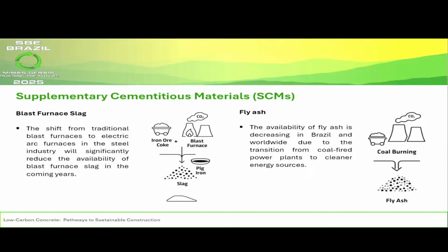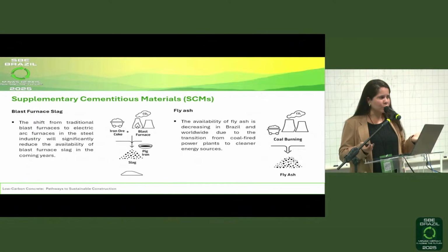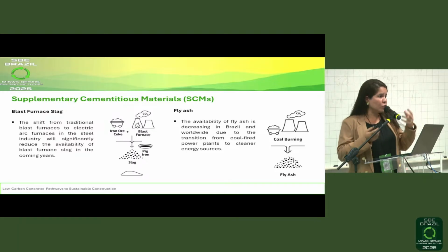The slag is amazing. I am a fan of blast furnace slag. It brings some benefits that cement wouldn't have if we don't use slag, but we have problems because the steel industry is improving its sustainability. They're not using blast furnaces anymore. Most of those furnaces are being turned off, and they're buying electric arc furnaces where we don't collect slag. So as years go by, we will have less available slag. Nowadays, it's not a problem to us, but it could be in the future.